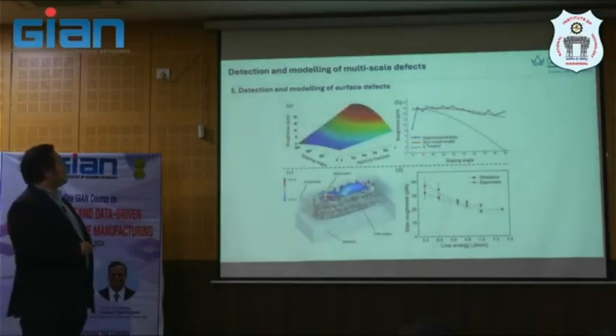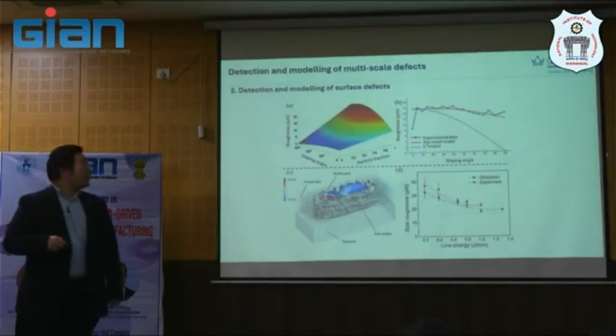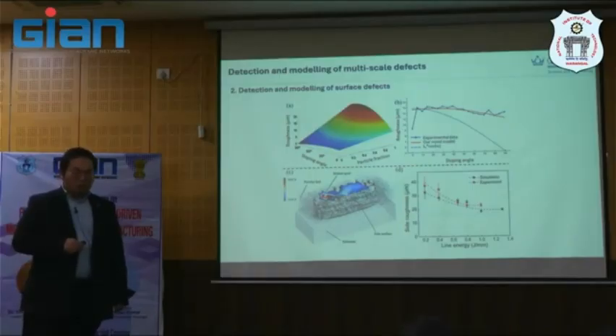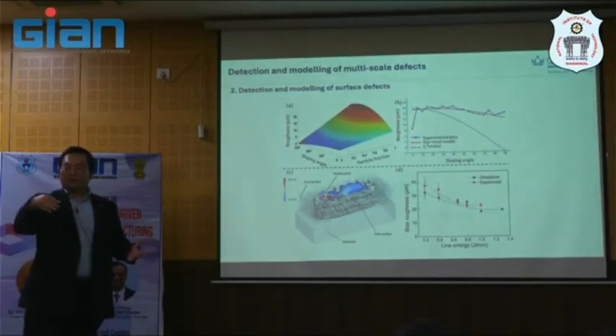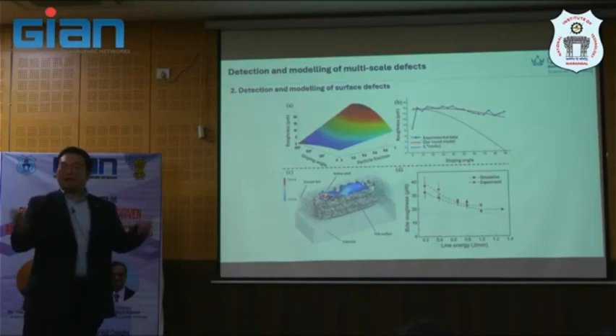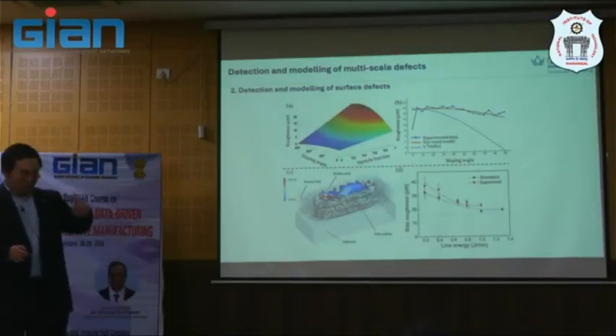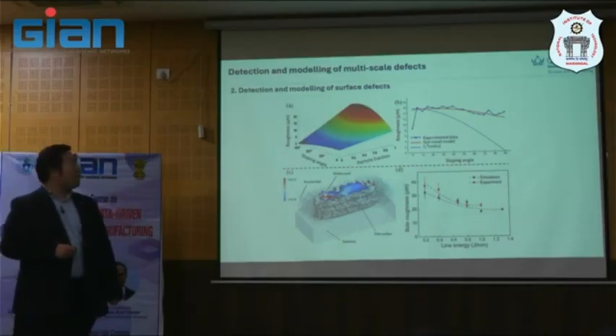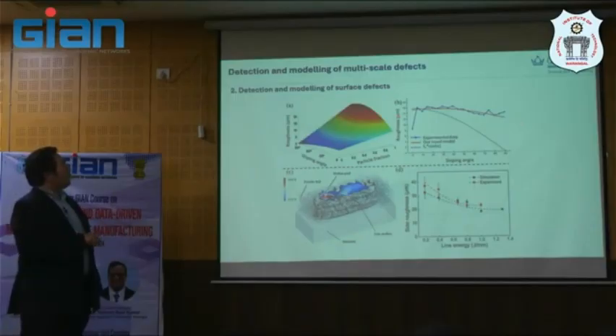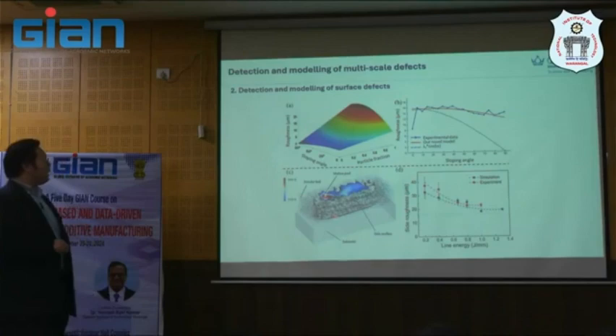And then next is prediction or detection of the surface roughness. If your printed sample is micro LPBF, for an implant for example, or thin film, you may use AFM, which is atomic force microscope, to detect or measure it. Or if it's large scale, it may be some kind of laser measurement. Previously my colleague that I collaborate with also used some microscope to roughly estimate. They measured Ra quite well actually, but I have to go back to see the information on how they did it. But anyway, this is some detection of the surface roughness, and the model can also try to predict what happened.